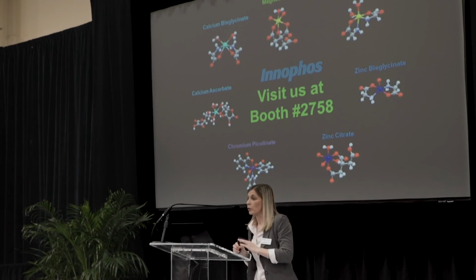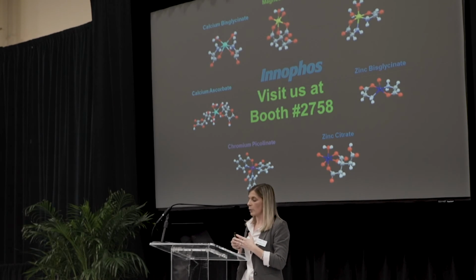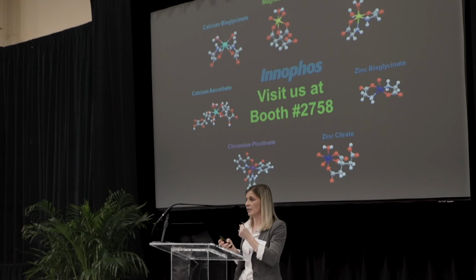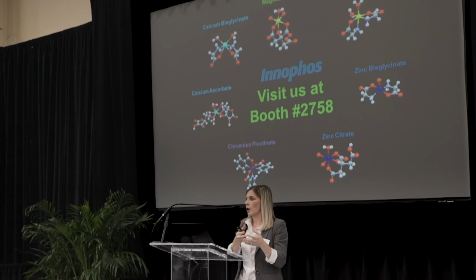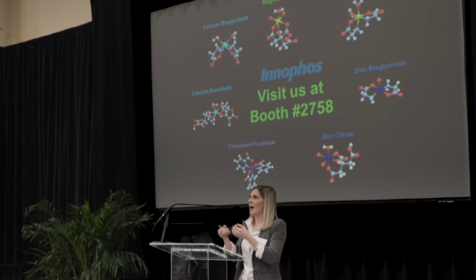The question is about the release of the chelate to then absorb the mineral. And so this is where with chelation, we can think of a lot of things like EDTA, right, that are great chelators and just latch onto these minerals and don't let go. But then that's not going to be helpful, right? Whereas something like glycine, citric acid, picolinate, they don't have binding constants that are so strong that they won't let go, but also not too weak that they don't stay intact. So it's a little bit of balancing something that chelates well, but not so tightly that it just never lets go. And so that's where there's the action of pulling that apart and breaking that down.